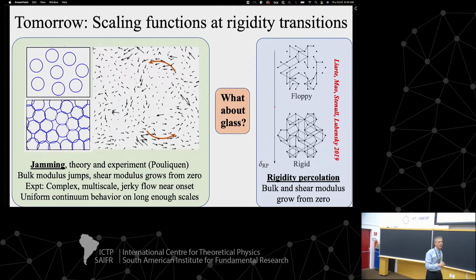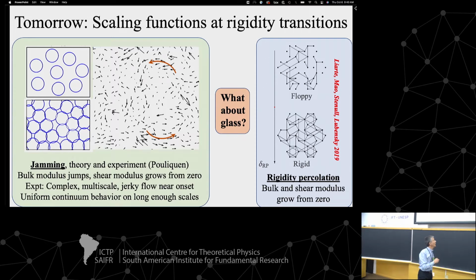But one of the things that makes rigidity percolation different is that here, as soon as these particles touch, if you have harmonic springs, which is a technical detail, the bulk modulus suddenly jumps. The bulk modulus behaves differently from the shear modulus. The shear modulus just grows linearly as you make the particles have more contacts as they start overlapping, and the bulk modulus jumps. In rigidity percolation, typically both the bulk modulus and the shear modulus disappear at the same time, and they disappear continuously.